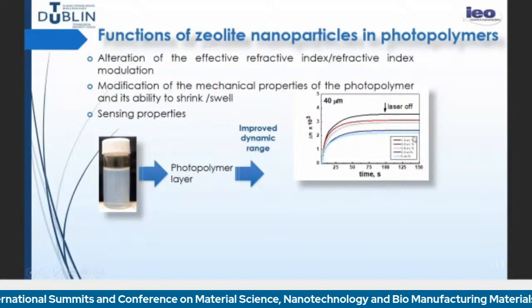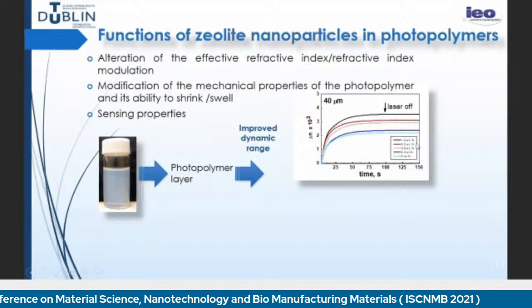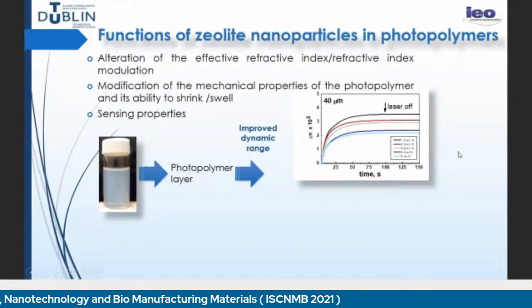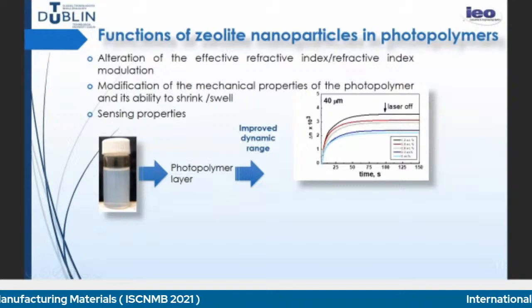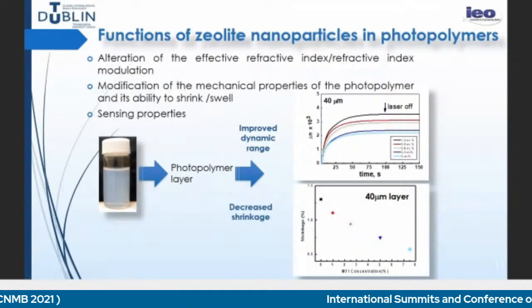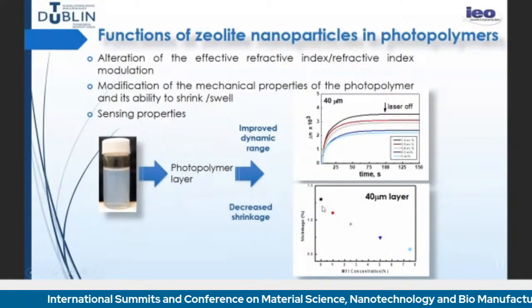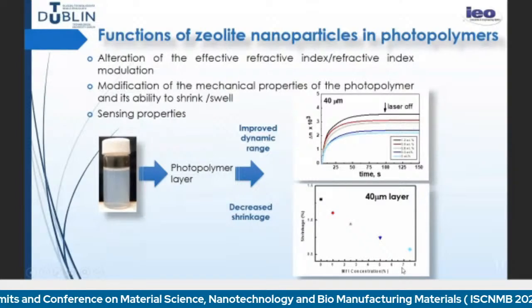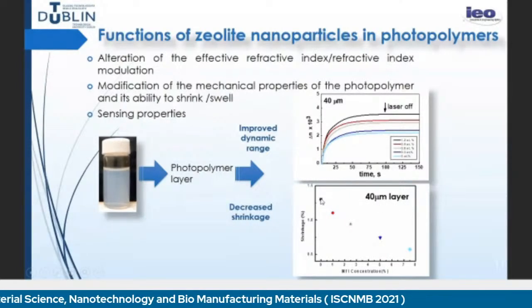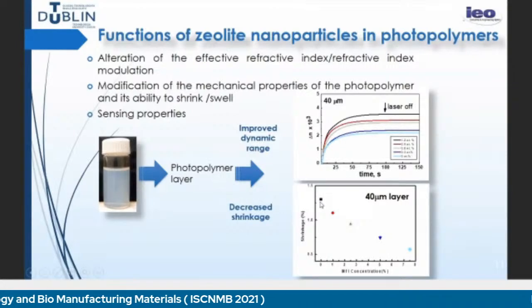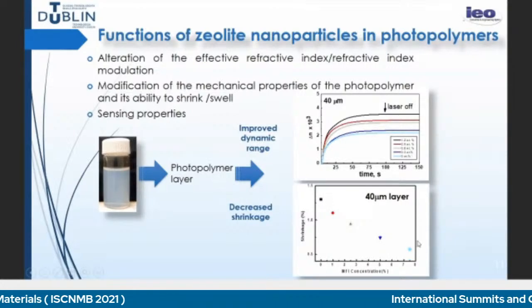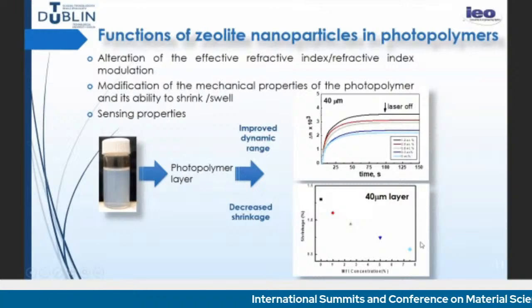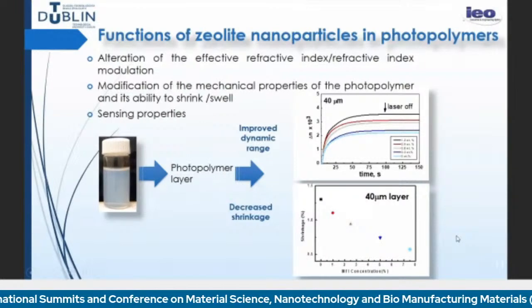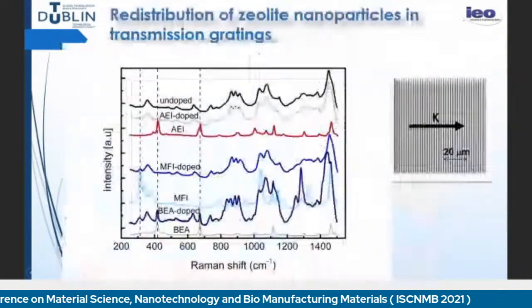This is a very small amount of nanoparticles in terms of weight percentage, but because these are porous nanoparticles, the volume that they occupy is much larger than 1.2 weight%. And in terms of shrinkage or mechanical stability of the layer, you can see how it is significantly improved by adding the nanoparticles. This is one type of zeolite nanoparticles in a 40 micrometer layer, and shrinkage is brought down from 1.3 to close to 0.5. For some applications like data storage, it has to be in this order, 0.5% shrinkage, even lower actually. How do we know that the nanoparticles are distributed?